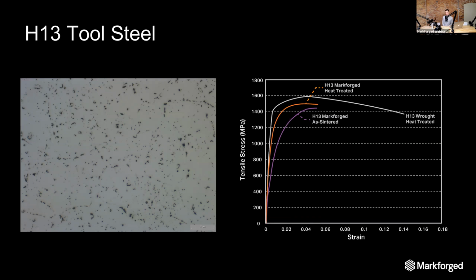H13 is a bit of a different story. You really, really want to heat treat H13, both to relieve stresses inside a part and to make it harder. An interesting thing about H13 is it's a two-process heat treatment. You're heating it up to about 1010 degrees Celsius, somewhere between that and 1030, and then you're air quenching it, so you just leave it out in air and let it cool down. That's the raw quench state. If you use it in that state, you'll get a really hard steel, probably in the neighborhood of HRC 50 for our printed steel, but something that's much more brittle.